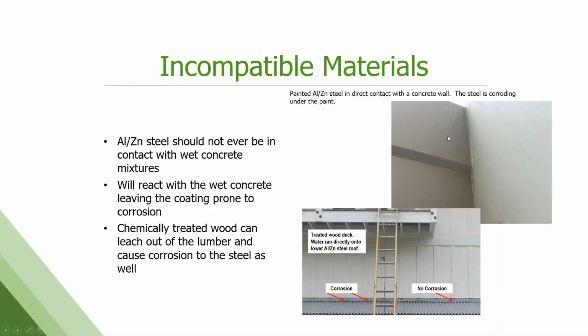So the example at the top here is concrete. The wall on the right is concrete, and then the galvalume panels on the left. You can see the corrosion blooming out from those contact points. They did not use a water barrier between them. And then this is a chemically treated deck, and where the water was running off the deck, we were getting corrosion down below on the panels at the next level. But as soon as you got away from that deck, it was fine.